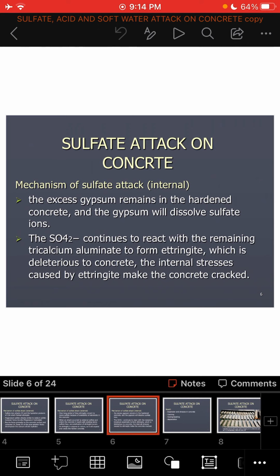As we discussed, gypsum reacts with the tricalcium aluminate to form ettringite. If excess gypsum remains in the hardened concrete, the gypsum will dissolve sulfate ions. These sulfate ions continue to react with the remaining tricalcium aluminate to form ettringite, which is also deleterious to the concrete. The internal stresses caused by ettringite make the concrete crack.